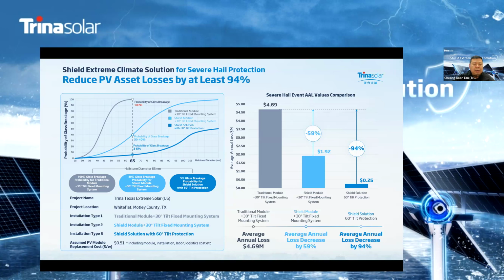So it's a 100% chance that you will get broken glass when a 65 mm hailstone occurs for installation type 1. But for type 2 and type 3, you can see the probability of glass breakage significantly declines, from a 30% chance of breakage to less than 5% chance of breakage in the 60 degrees tilt protection.